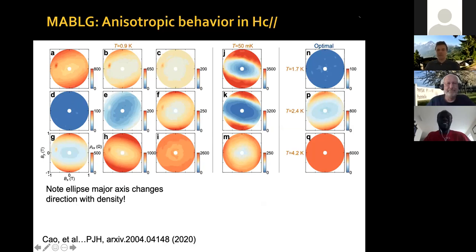But for example, at optimal doping, even at 1.7 Kelvin we cannot see the ellipse, but if you increase the temperature to 2.4 Kelvin, now we can see the ellipse, okay? So at base temperature, we have to choose a doping where we have very low Tcs so that we can measure these ellipses. And at intermediate temperatures, we can see an ellipse over a variety of dopings like here, okay?